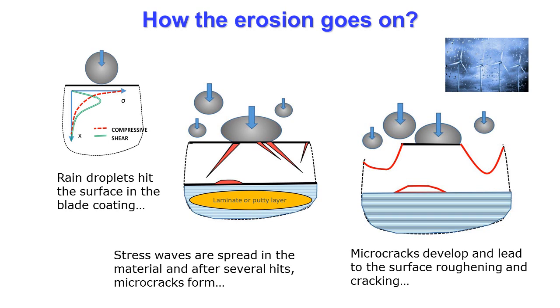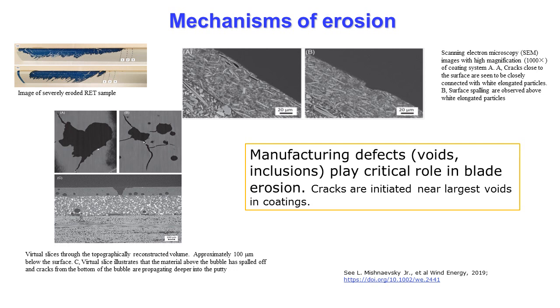Rain droplet impacts. We at DTU carried out detailed microscopy studies of eroded blades. Samples from eroded blades were cut, and scanning electron microscopy and X-ray studies were carried out. The experiments were followed by computational modeling. We observed that the erosion was always triggered by local manufacturing defects. In the places where the coatings had large voids, or inclusions with weaker interfaces, the erosion started.